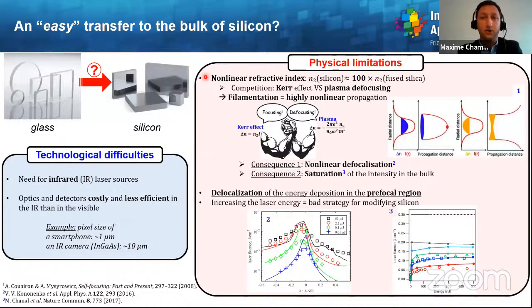It is about 100 times higher than that of fused silica, which means that during the propagation of the laser pulse, there will be a competition between the Kerr effect on the one hand, which focuses the beam, and plasma defocusing on the other hand. So you focus the beam, the material starts to be ionized, and this ionization provokes a defocusing, which is called plasma defocusing. In other words, we are in the filamentation regime, which is a highly nonlinear propagation regime. I would not say the word chaotic, but you get the idea, I hope.